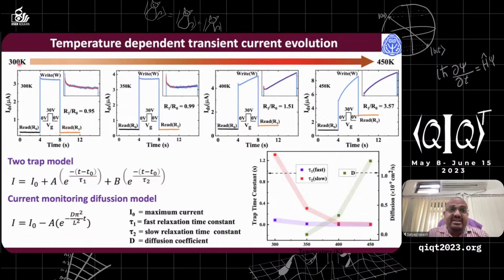When it is at 300 Kelvin, suppose we consider this the read current, and this the write current when the pulse voltage is there. You see here both sides read, R1 and R0, are the same. But when we increase the temperature and go up to 400 Kelvin, you can see a dramatic change in the read current. Here it was the same on both sides. Now, at 400 Kelvin, you see the read current is picking up and it is higher. Now at 450, it is much higher, which is consistent with what I showed previously, where it undergoes a reverse hysteresis.